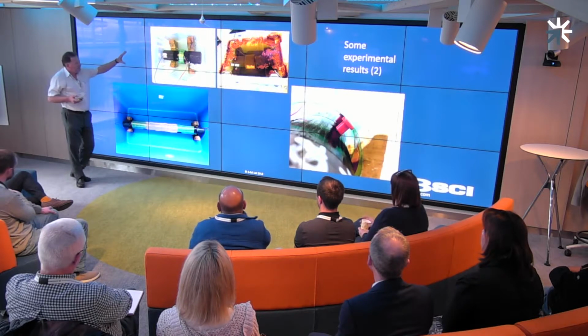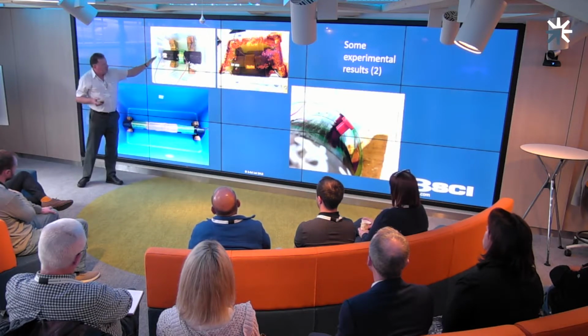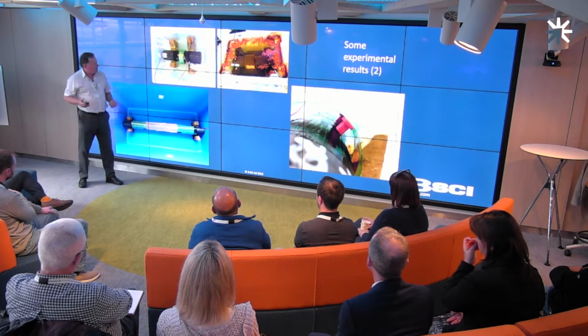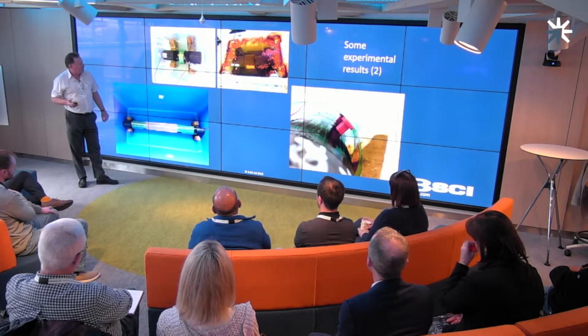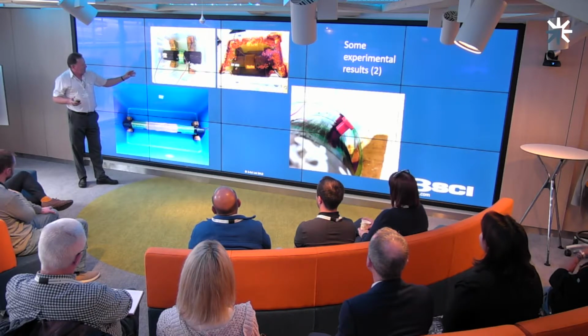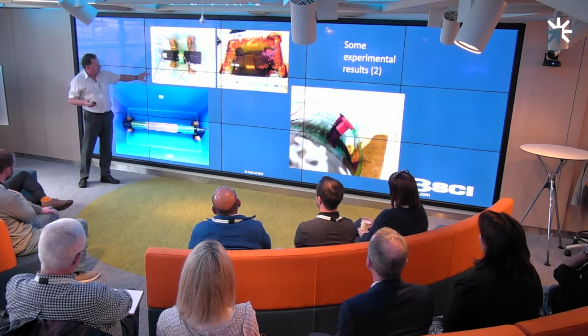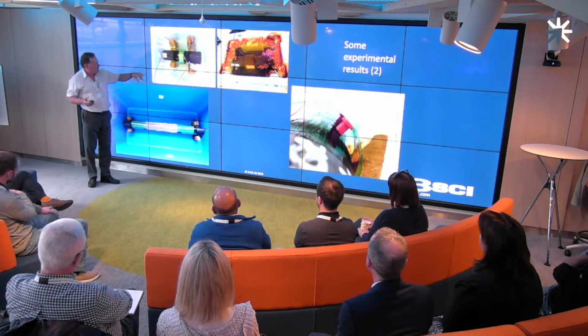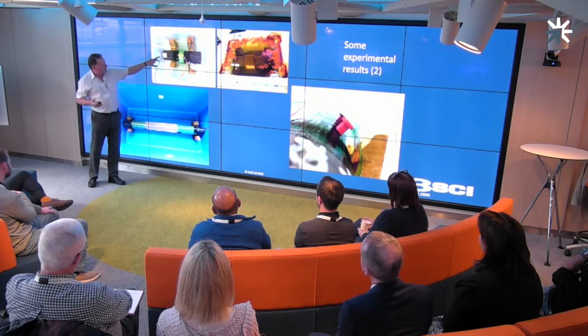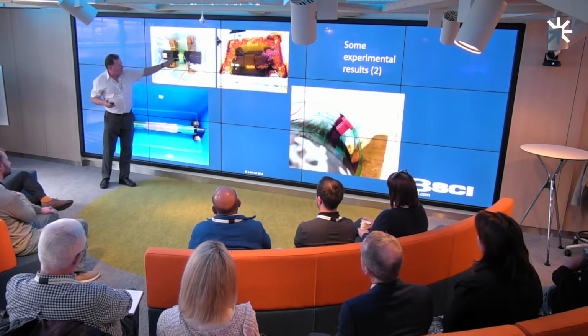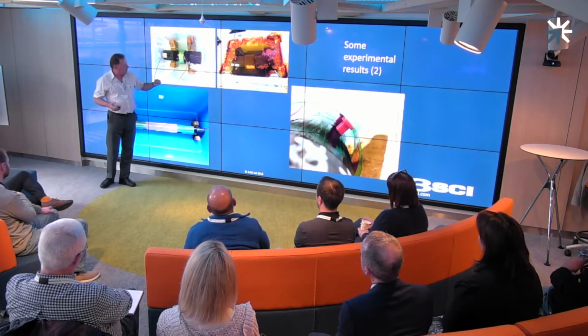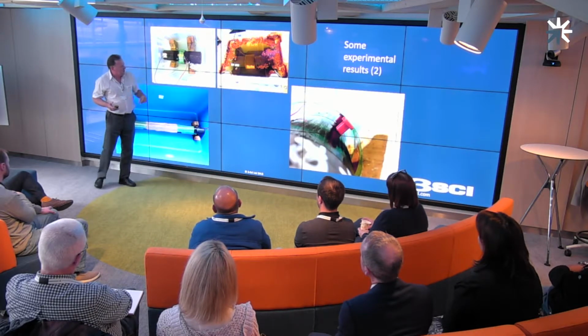Relatively small tanks of water, tubes about that big, about 1/2 meter or a meter long, and typically 10 or 20 centimeters diameter. It's a bit unfortunate, this one, do excuse me, we've actually got the wires the wrong way around in terms of the colour. That should be the red wire pumping positive current into the steel. And this should be the black wire delivering current back to the negative of the battery pack, excuse this image. And then the cathode as an annular ring placed around the steel.